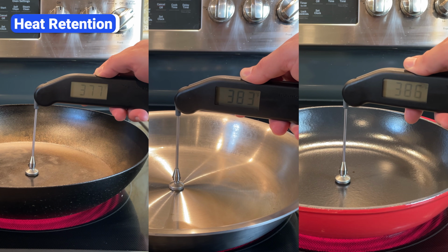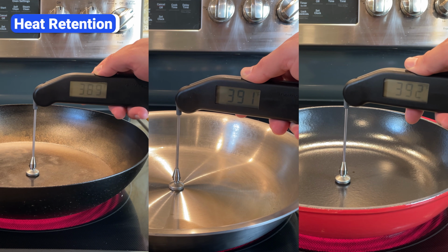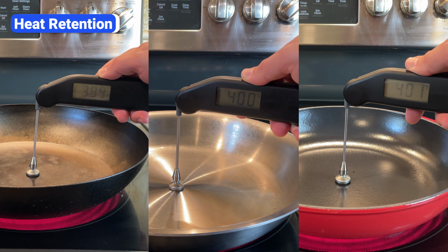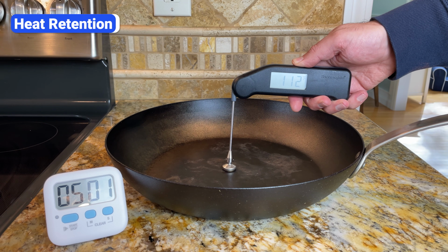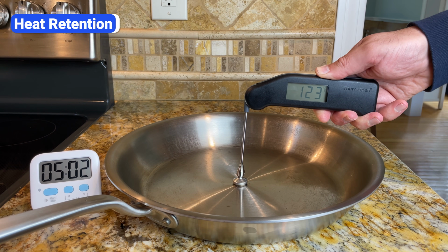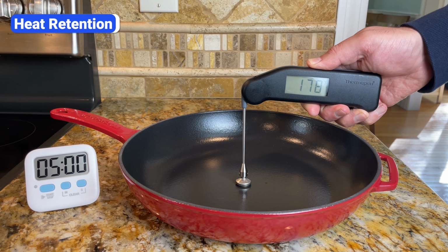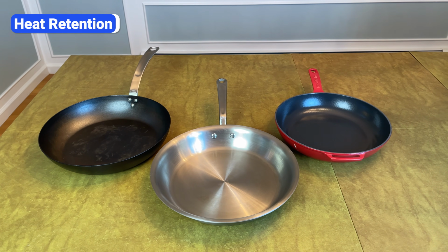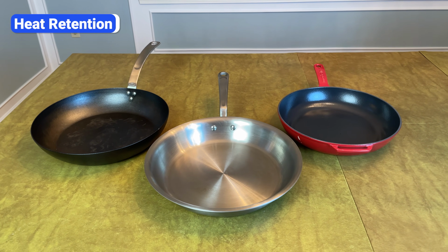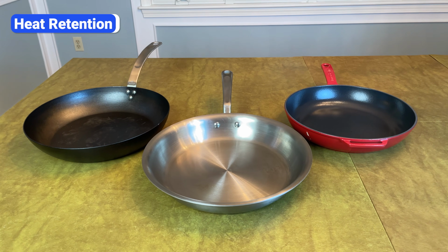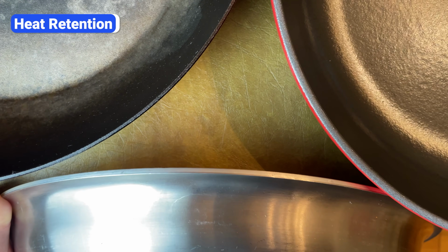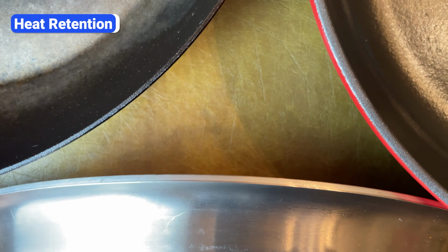Another factor to consider is heat retention. To test this, I heated each pan to exactly 400 degrees Fahrenheit before taking it off the burner. After 5 minutes, the surface of the carbon steel pan was 112 degrees Fahrenheit. The stainless steel pan was 123 degrees Fahrenheit, and the cast iron pan was 178 degrees Fahrenheit. These results didn't surprise me because heat retention usually aligns with thickness. Although it varies by brand, in the case of Made In, their cast iron pan is by far the thickest, followed by stainless steel and then carbon steel.